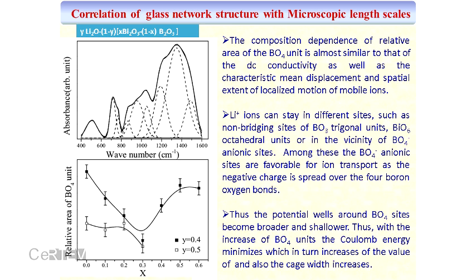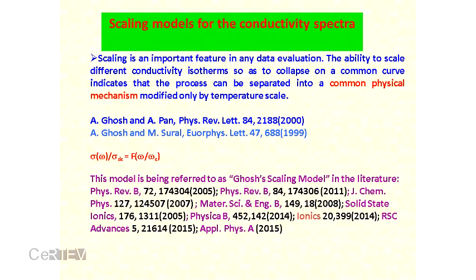Now I shall describe the scaling model for the conductivity we have developed, because scaling is an important feature in data analysis. It is the ability to scale the conductivity isotherms at different temperatures, in a conductivity range, temperature range, or frequency range, superposing onto a common curve. That indicates that the process can be separated into a common physical mechanism that is modified by the temperature scale.